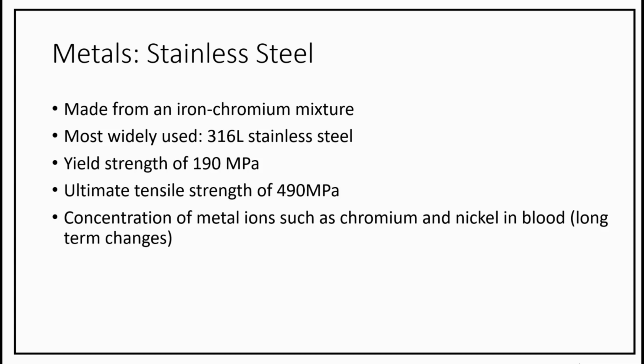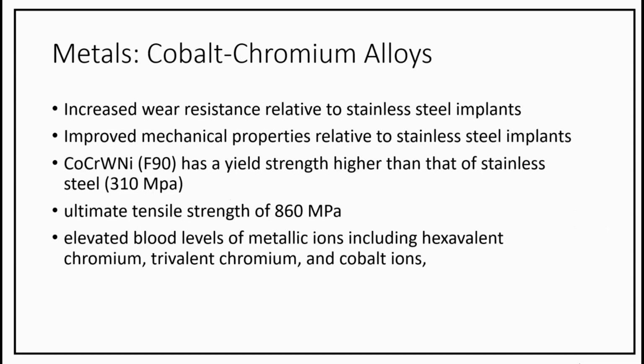With in vivo testing, stainless steel implants have been noted to produce longer-term changes in blood composition, particularly regarding the concentration of metal ions such as chromium and nickel. Cobalt-chromium alloys are an attractive alternative to stainless steel. Their increased wear resistance relative to stainless steel implants and significantly improved mechanical properties have made cobalt-chromium alloys one of the most utilized materials for total hip and knee replacements.